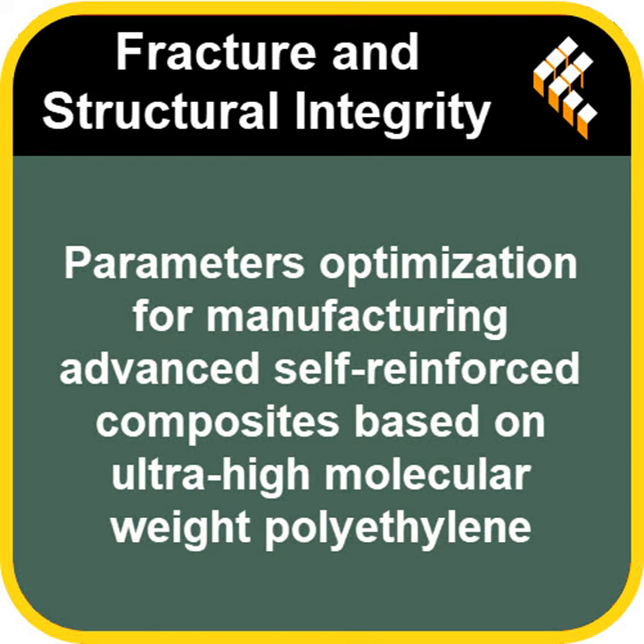That sounds ductile. Exactly. It's a ductile response, which is a huge contrast to, say, traditional composites made with UHMWPE fibers in a brittle epoxy matrix. Those tend to shatter. And did the impact resistance change with temperature? It did. It got progressively better as the processing temperature increased up to that optimal range again. It went from about 72 kilojoules per square meter at 145 C up to around 95 kilojoules at 165 C. So better bonding helps it absorb impact energy better too.